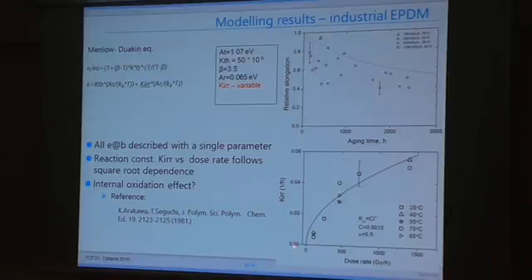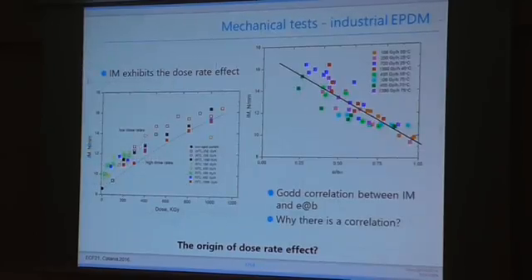Also, this constant is found to be very dose rate dependent, and moreover, this dose rate dependence is found to follow the square root. And this is important because in previous investigations it was found that this square root dependence might originate from the oxidation effect. The second very interesting test is indenter modulus, which is important because it is a non-destructive test. The indenter modulus increases with dose, so it increases with aging, and again we can observe dose rate effect. We can observe a faster increase for low dose rates in comparison to the high dose rates.